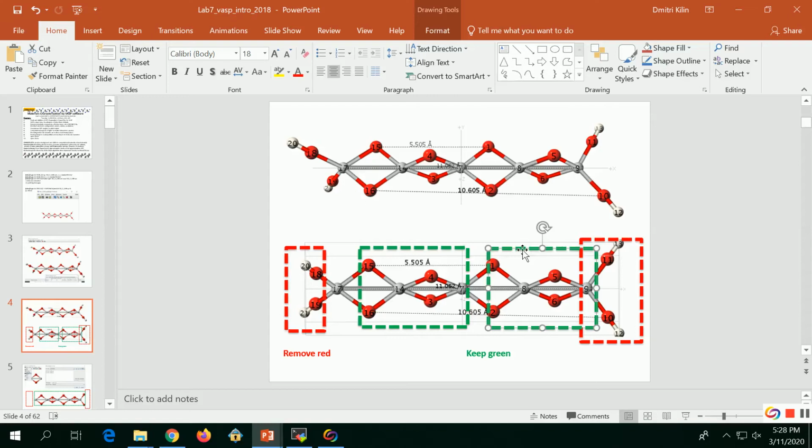If one doesn't do it, it will be like a simulation cell where atoms are jammed close together, which will immediately shrink the gap to zero if it was a dielectric, or expand it to a very large value if it was a metal. So it will be very wrong results.